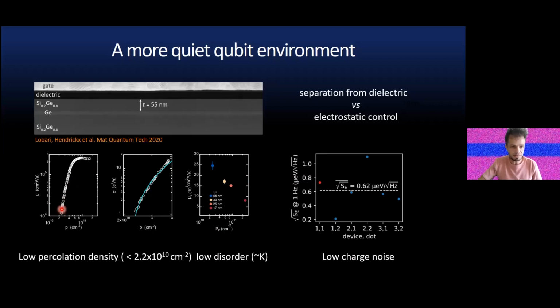Here you see you still have a very high mobility, around 200 or 300,000, at high density. But most importantly, you can achieve really low density, like 2 times 10 to the 10. You're starting to rival III-Vs here, especially considering you have a full gate stack. This is not modulation doping, which doesn't have any dielectric. So this is fully tunable. This is actually one of the lowest percolation densities out there in group IV.